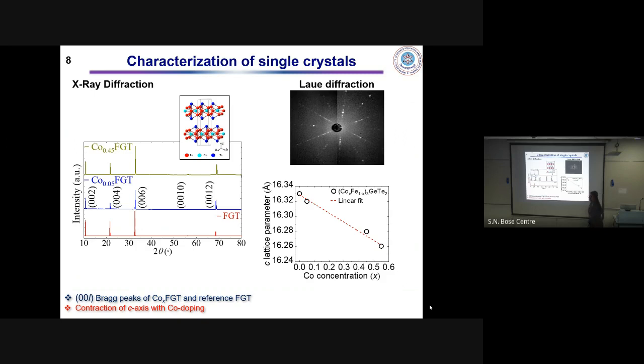How did you do that? You extracted only the C parameter? Not from fitting, it's powder XRD. There was a little bit of a problem because in these kinds of systems it is not easy to powder. So we powdered it for around 2 to 3 days, and then did XRD. And from the Rietveld refinement we could get the a, b, c.